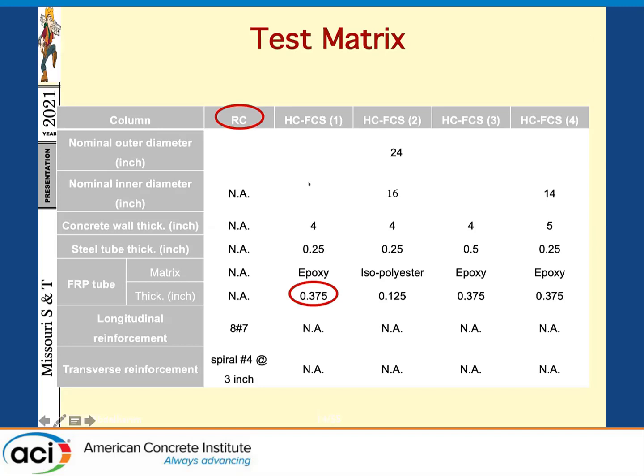The first parameter that we changed was the thickness of the FRP. The FRP tube was one of the most expensive constituents of this column. So we tried to optimize the thickness. Over here, the common one was 3/8 of an inch thick tubes, while on one of the columns we went to 1/8 of an inch.